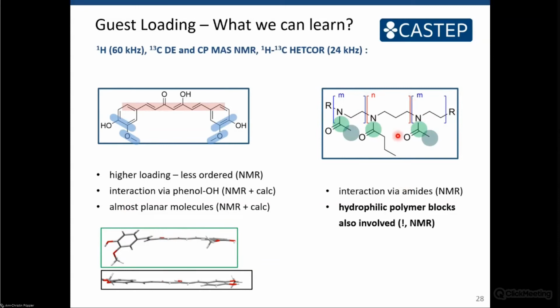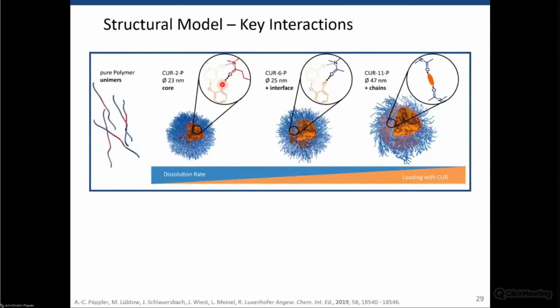And the most curious thing in the study was that while this molecule is fully soluble and we would expect it to be in this red part of our particle, we also saw changes for these hydrophilic parts. And this helped us. Well, at first it was surprising, but it helped us to explain all the properties, because if you load more and more molecules inside of the core of this particle, at first you have lots of coordination sites available. They become more and more saturated. And when you have all the coordination sites in the center used up, then you will need the hydrophilic parts of the polymer to stabilize the particle.